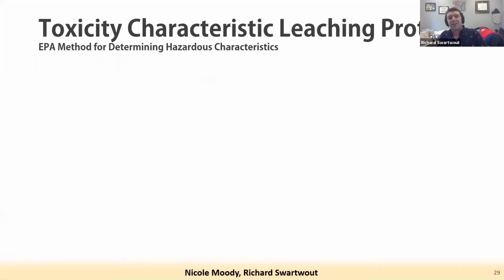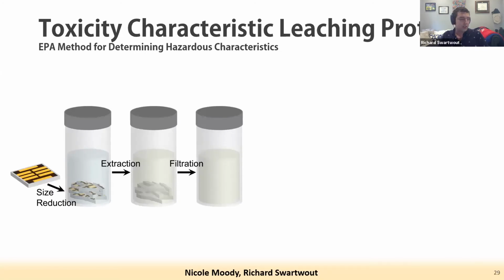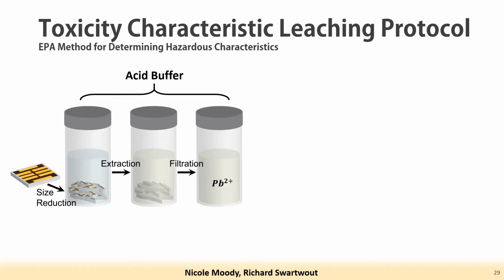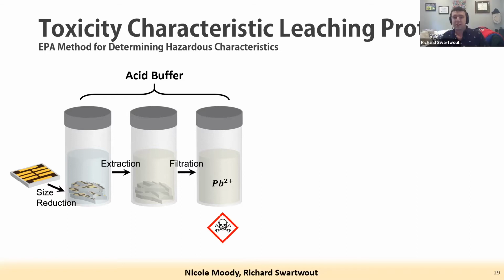The real test is the toxicity characteristic leaching protocol, or TCLP. It's a regulated test with meaning, tied to regulations on what you can and cannot do with products. You take a product of interest, deliberately reduce it in size to simulate extreme degradation, then extract it with an acid buffer to simulate acid rain and acidic ground conditions. Filter off everything soluble, then look at the solubilized lead, which can potentially harm people through groundwater.